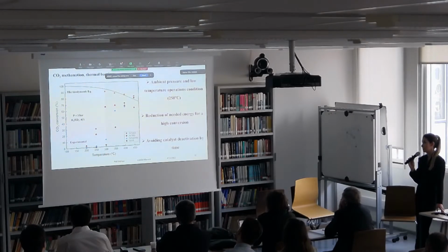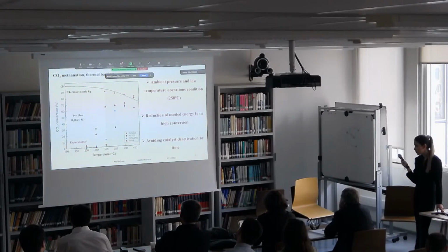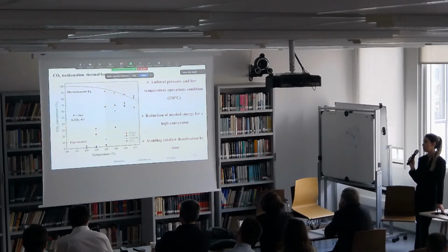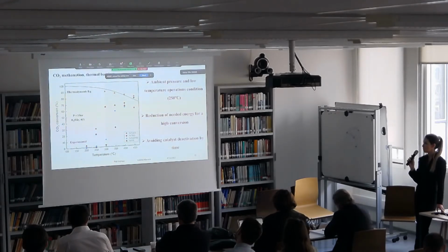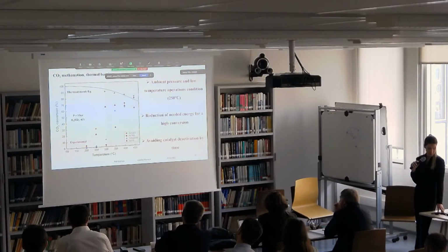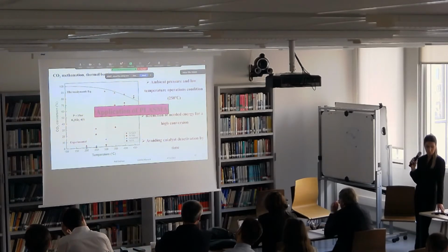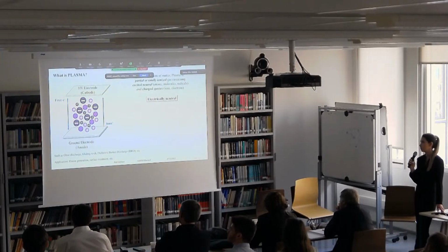So as we saw the barriers, we could say that CO2 methanation should be done at atmospheric pressure and low temperature in order to have a high conversion. By some method, the needed energy should be reduced in order to have high conversion and avoid catalyst deactivation over time, as catalysts start sintering at high temperature. By this means, plasma can provide all these conditions for us in order to have good catalytic performance. However, what is plasma?